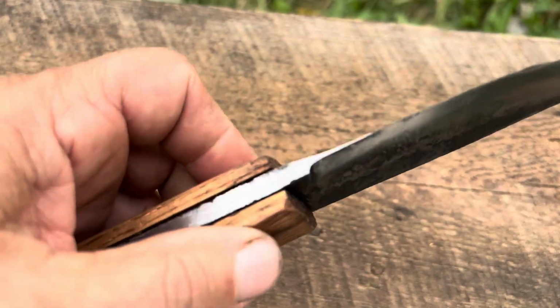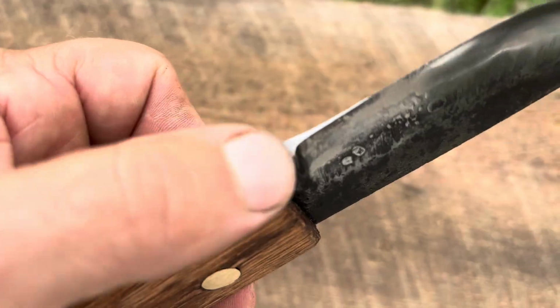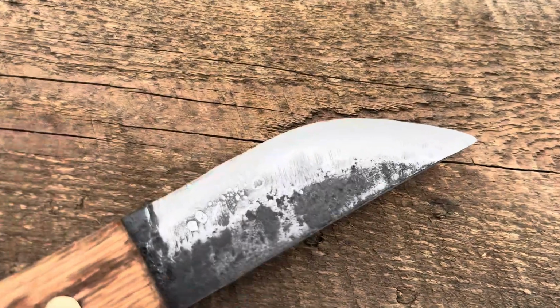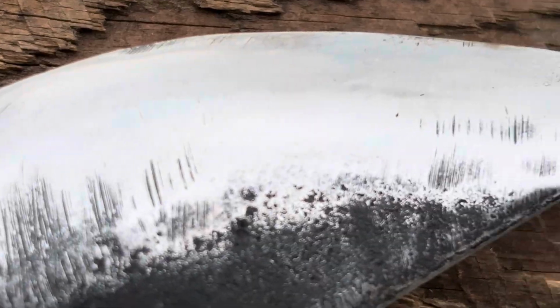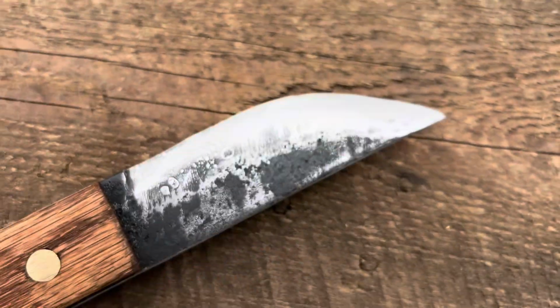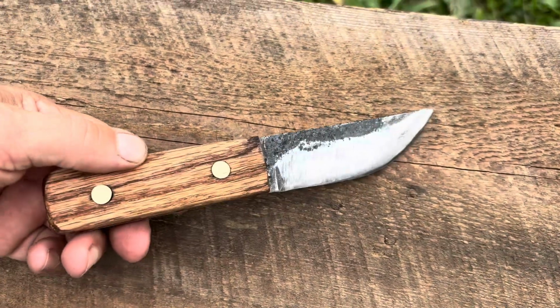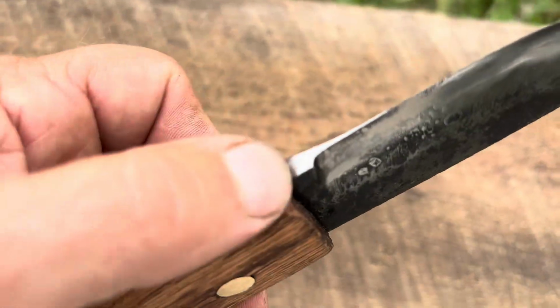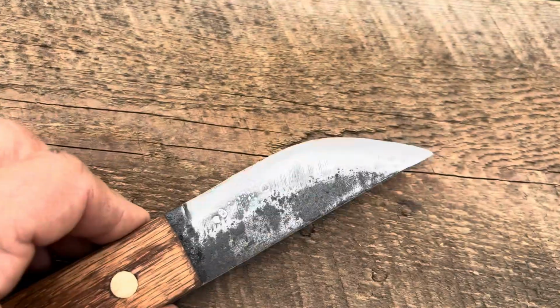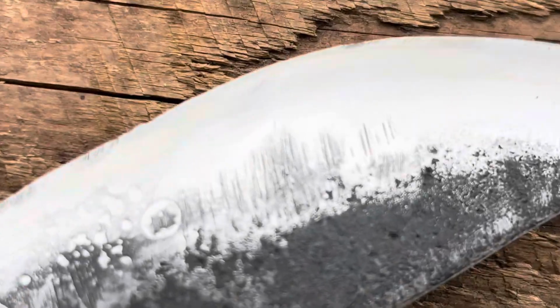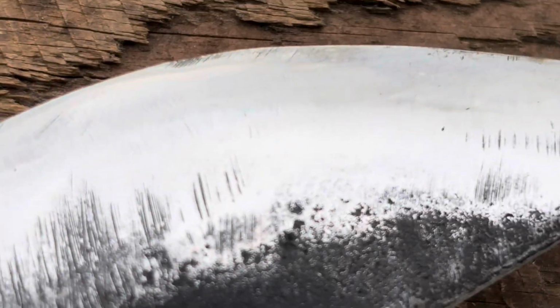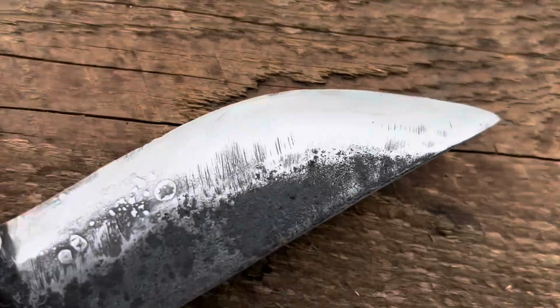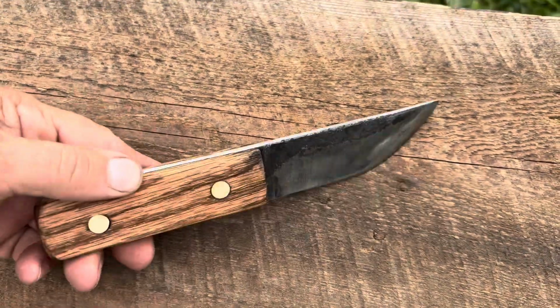And you can see it's not perfect. I should have worked on these plunge lines a little more before the heat treat, but I can fix that. And you see these scratches from the heavy grinder, obvious, but this is not meant to be a display piece. This is a heavy use knife for bushcraft and survival. It's going to be batoning, it's going to be left out in the rain, and it's going to survive a beating a lot better than a lot of knives that I've spent $100 or more on.